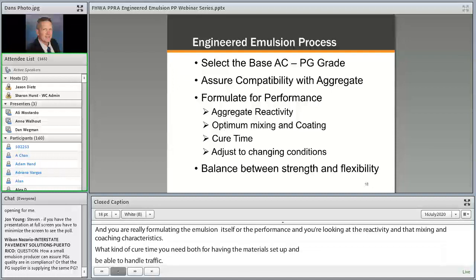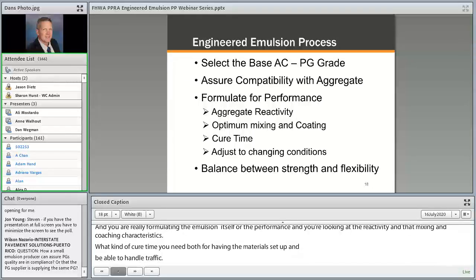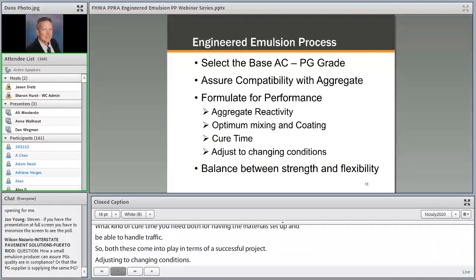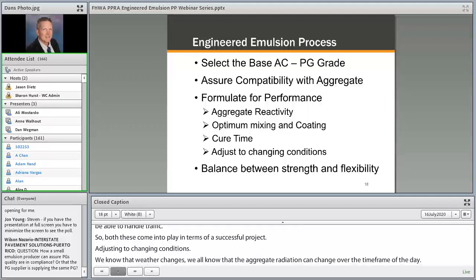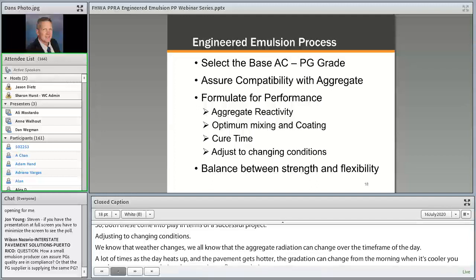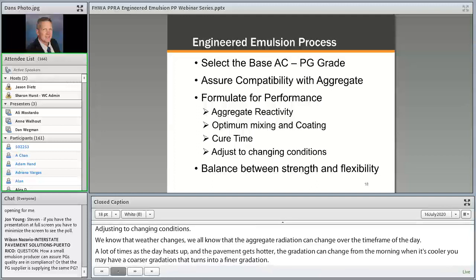And then adjusting to changing conditions. We all know that weather changes. We all know that the aggregate gradation can change even over the time frame of the day. A lot of times as the day heats up and the pavement gets hotter, the gradations can change. From the morning when it's cooler, you might have a coarser gradation that turns into a finer gradation. So not only adjusting to those types of conditions, you need to adjust the emulsion content in some cases, and if you're talking about something like a microsurfacing, you might be adjusting the formulation on the fly as well. And the key here for in-place recycling is really that balance between strength and flexibility.